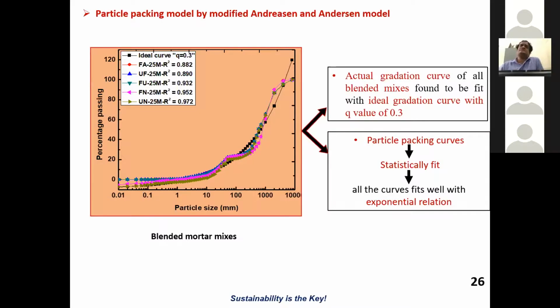These are plotted here just to understand how well my mortar mixes fit the ideal curve of modified Andreasen and Andreasen. You can see the black one is the ideal curve, and all the proportions I have taken are very closely fitting, even statistically, with the ideal curve. So that is the way I can validate that the mix I have taken ideally fits the curve given by the modified Andreasen and Andreasen model.